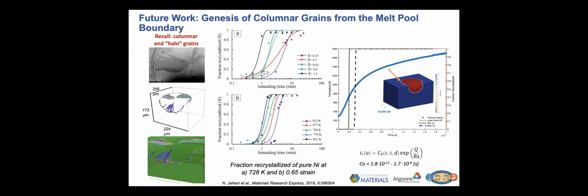And now we understand from Flow3D the local temperatures that are experienced in the melt pool. And one thing that was of a concern to us is the explanation for these grains. It doesn't seem like they come from columnar to equiaxed transition. And so we went and we took a look at recrystallization as being a possibility.